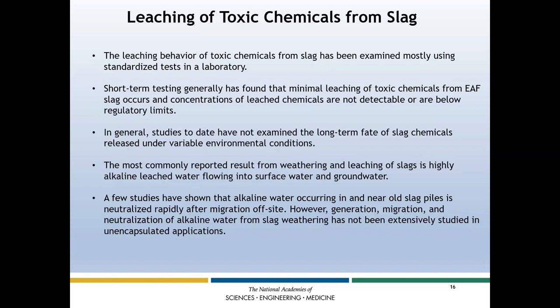In addition to the particles, there's concern about leaching of the toxic metals from the slag, and that has been examined, mostly using standardized testing in a laboratory, not out in the environment. Short-term testing has generally found that minimal leaching of toxic chemicals or metals from the EAF slag occurs. And concentrations of the leached metals are not detectable or below regulatory limits. In general, studies to date have not examined the long-term fate of slag chemicals released under variable environmental conditions.